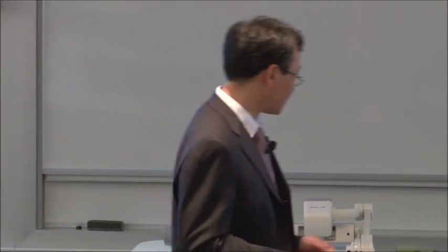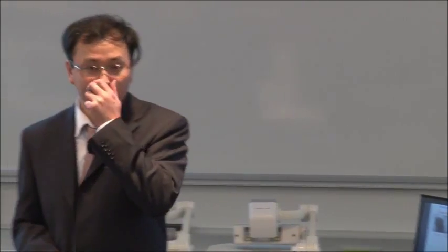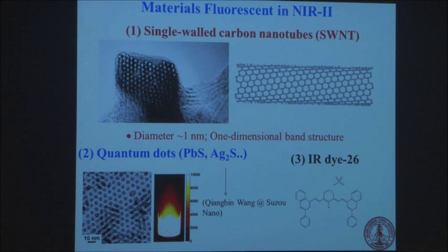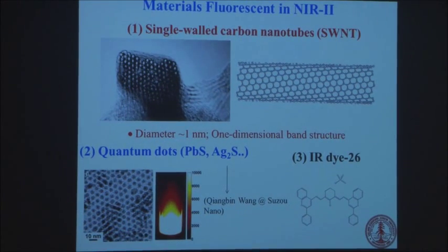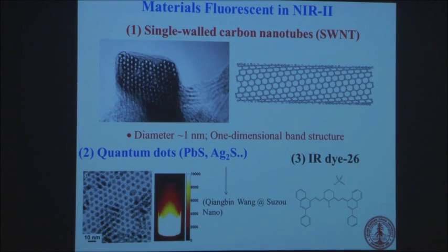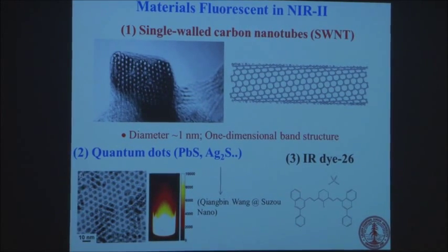So for a long time, nobody really cared about this region, even though they knew the absorbance is low and you can still use it. Not many people realized that this part is actually quite important if you want to do good imaging. Carbon nanotubes, as I said, are one of the things that emit in this window. There are also quantum dots, lead sulfide, silver sulfide, which emit at about 1200 nanometers, or you can tune them by composition or size. And there are organic molecules as well that can emit at such a wavelength. This is one example, and I'll show you another example later.